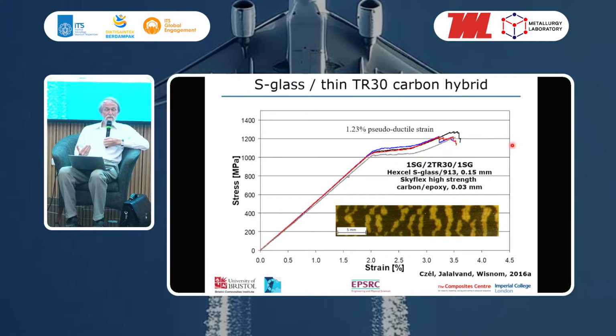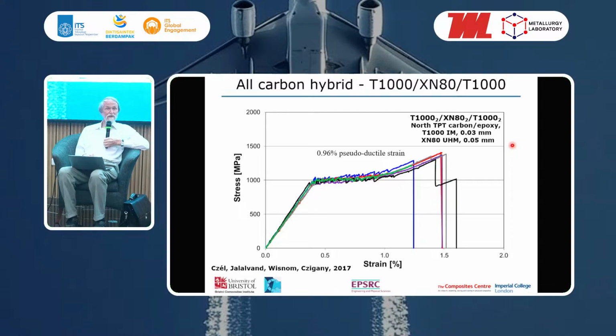So this is an example for glass and standard modulus carbon, but we can do the same thing with different grades of carbon. This next plot shows 2 different types of carbon, where we're mixing a T1000, which is an intermediate modulus carbon, and XN80, which is a very high modulus carbon, mixing those 2 different carbons together in this thin ply hybrid, where all the plies are quite thin. You see again a similar behavior with this plateau on the stress strain curve, a lower initial failure strain because this is a high modulus material, and again a plateau with about 1% pseudoductile strain there. So this is a very interesting response that we've been able to achieve by hybridizing these thin ply materials.